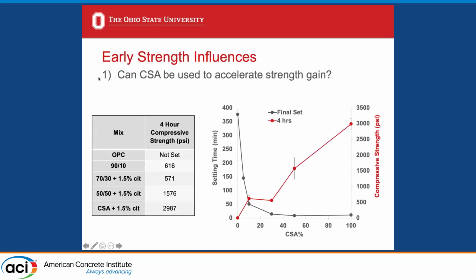Right. So at the beginning, I postulated that perhaps we could use CSA as an accelerating admixture, and this slide shows the results of that. And what you can see is we were not able to obtain the 4,000 PSI rapid repair conditions that we had hoped for in this mix, but we can see that with increasing amount of CSA, so we go from 0 CSA at the top to 100% CSA at the bottom, it's quite linearly related how much CSA you have versus the rate of strength gain initially.